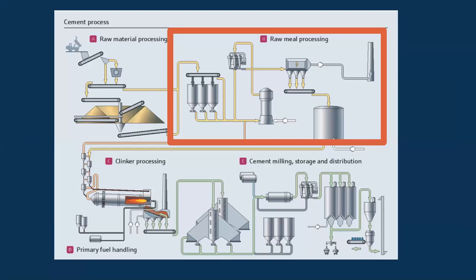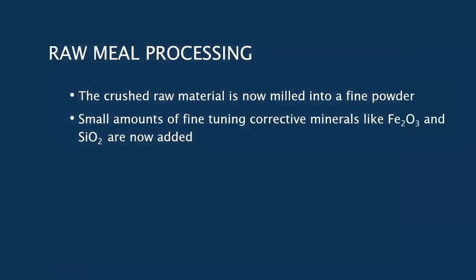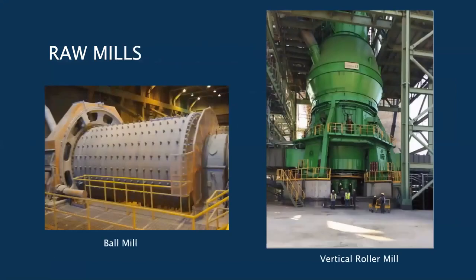Raw meal processing: once the raw material is crushed, it is now milled into a fine powder. And final fine-tuning is now done by adding corrective materials with iron and a bit of silica at this point in time. The milling of this stuff is done by either a ball mill, more in the older days, and today we see more and more of these other ones, which are called vertical roller mills. You can see the size of the thing if you look at the people down the bottom here.